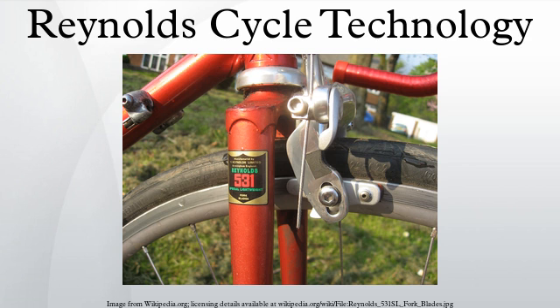531, manganese molybdenum. UTS 700 to 900 MPa, density 7.85 grams per cubic centimeter. 531 ATB, designed for mountain, all-terrain, off-road. 531C, competition racing tube set for road racing, track, time trial and cyclocross. Main tubes were 88 double-butted, slightly thinner than Columbus SL.